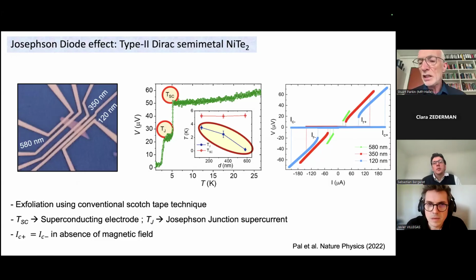And we have voltage versus current curves for these three junctions on this same flake, which are separated by 120, 350, and 580 nanometers. And so you can see as the spacing is increased, with 580 nanometers, that's half a micron, we can still flow supercurrent, but the critical current density will be reduced, as you can see here.